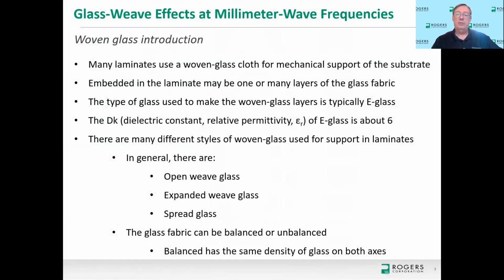So to start as a quick introduction, the woven glass fabric or the fiberglass that's used in the printed circuit board industry, it's typically used as mechanical support for the laminate. And there are several benefits to the woven glass layer. And there's also some drawbacks, which is true with just about anything in engineering. Everything has pros and cons. So the woven glass is helpful for supporting the structure mechanically better for the laminate, and also having the laminate having a little bit better dimensional stability, more consistent dimensional stability, things like that. But the drawback can be having Dk differences due to the glass fabric itself.